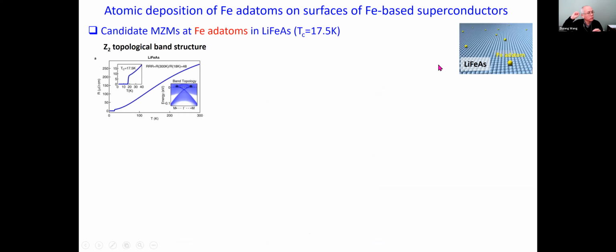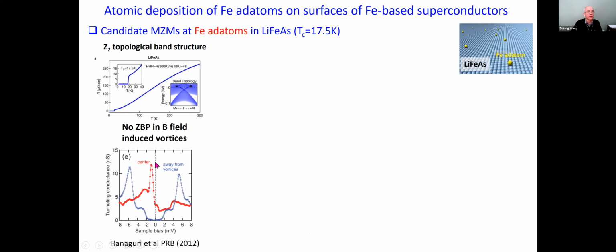They did atomic deposition of iron atoms on LiFeAs, which has been talked about quite a bit at the symposium. 111 has a Z2 topological band structure. In fact, yesterday we heard it's actually quite intriguing. And Hanaguri did the vortex measurement quite early on. The blue line is away from the vortex, and the red one is at the vortex, in the vortex center. You don't see a zero bias peak. In fact, the vortex seems to be gapless.